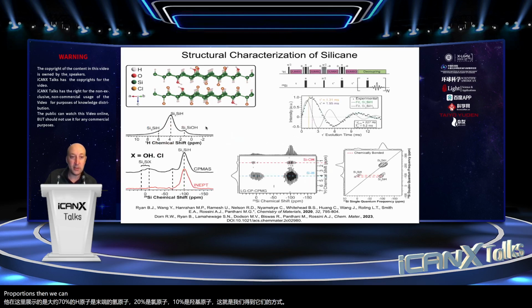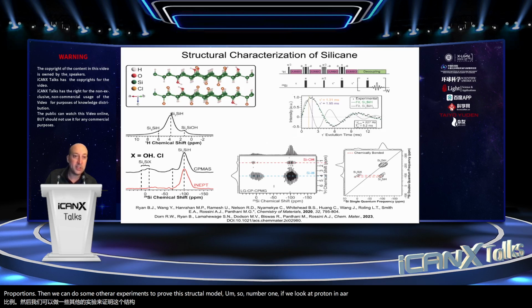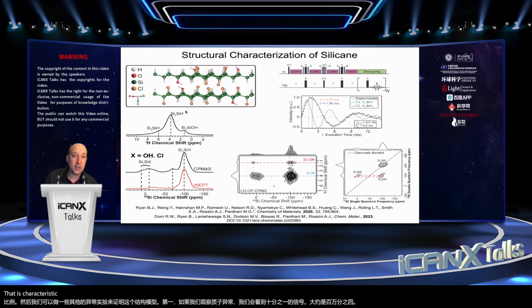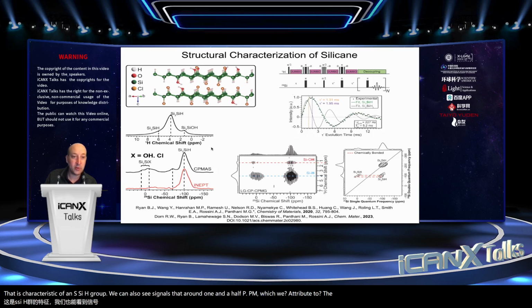And then we can do some other NMR experiments to prove this structural model. So number one, if we look at proton NMR, we see one set of signals at about 4 ppm. That is characteristic of an SiH group. We can also see signals at around 1.5 ppm, which we attribute to the hydroxyl groups.